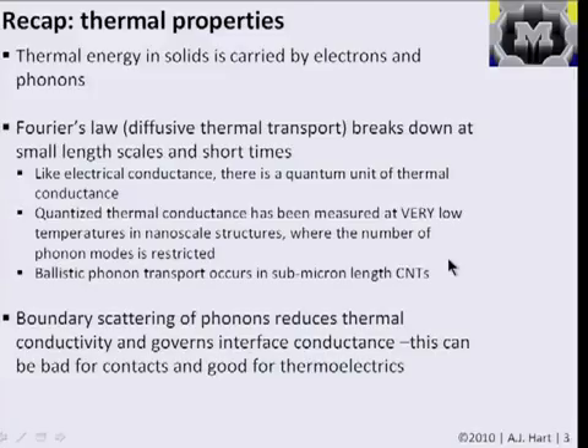And perhaps more practically over a wider range of length scales, the scattering of vibrations at boundaries can affect the thermal conductivity. And we saw for the second time the example of things like thin films, where if you scale down the thickness of a film, the conductivity can change. And the same principle is important for contact between interfaces. For example, if you're putting two materials together, the contact resistance is governed by the roughness of the surfaces, and also at the nanoscale, a physical match between the ability of one material to transfer vibrations to the other material. And this can be very practically important for things like thermal interfaces.